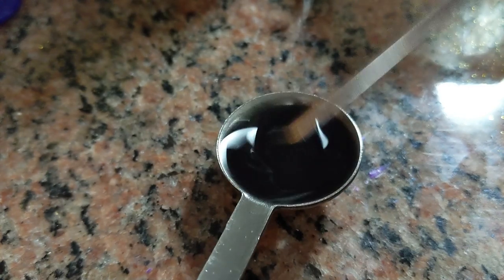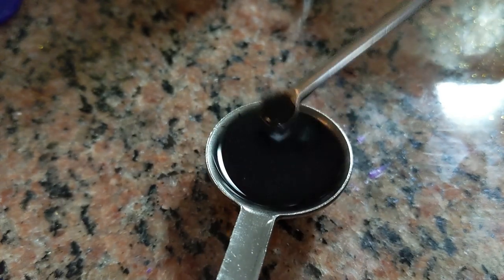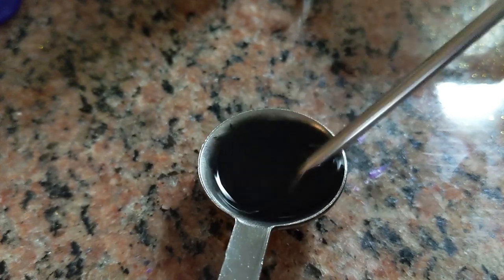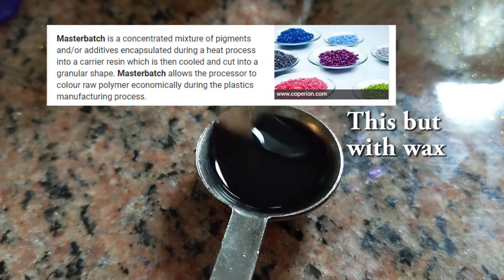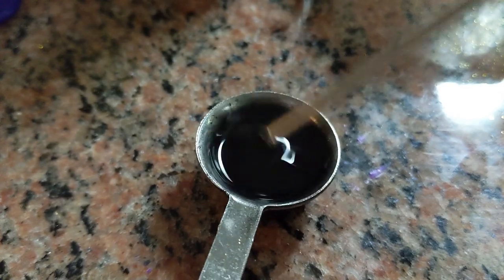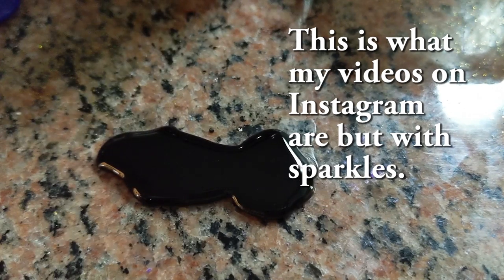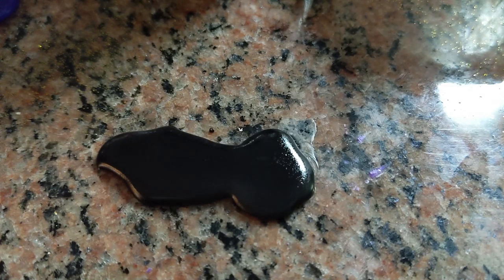This is me creating a master batch. Later in the video, you're going to see me using a solid pigment and that pigment is being made right now. A master batch is when you mix a strong pigment with a component of your final product so that you can add the pigment without adding too much — it gives you better control over it. I am using oxide pigments. This is an oxide black, so it's not mica based and it's very strong, so I'm watering it down a little bit, making it a little easier for me to control.